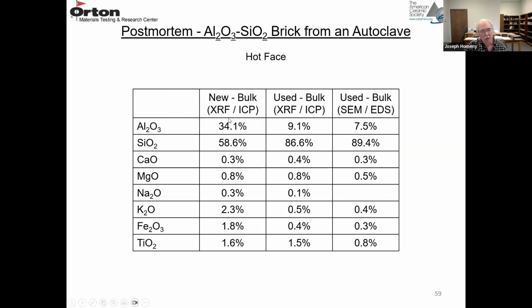So we had actually had a new brick here, and we did a bulk chemistry by XRF ICP on the new sample, and it has like 35% alumina, almost 59% silica, and then your typical impurities that you'll see in a clay. So this was a clay-based aggregate bonded by the same clay in the matrix. But then the bulk chemistry from the hot face and then the SEM from the hot face show a different composition. So if you look at the Al2O3 content, whether it's bulk chemistry or from the SEM, it's down from about 34 to 9 or 7 or 8%.